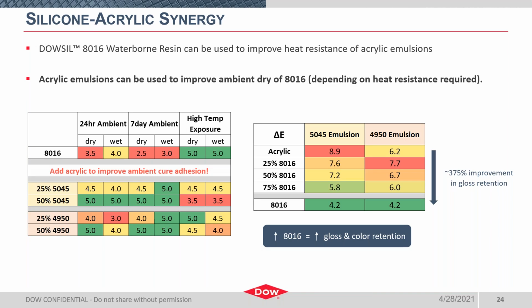Here, let's start by looking at the table on the right. This is color change data, or delta E, after high temperature exposure. The left column indicates how much silicone and acrylic are in the formulation. The top row is all acrylic, and then the silicone content again gradually increases as you move down the table until you get to that last row, which is pure 8016, similar to what I showed on the last slide. The right 2 columns show delta E for the 2 acrylic emulsions, 5045 and the 4950. And the conditional formatting in this case is again vertical. So we're comparing all the 5045 column to each other and not to the 4950 data, and vice versa.